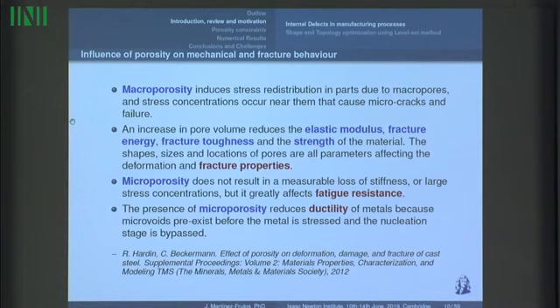Also, the size of the holes is related with the degradation in the elastic modulus, fracture energy, and fracture toughness. So macroporosity is related with failure of fracture. On the other hand, we have microporosity. This microporosity does not result in a loss of stiffness or stress redistribution, but greatly affects fatigue and ductility. So those are some of the consequences of having these kinds of defects inside the structures.